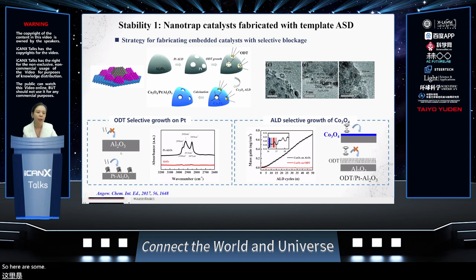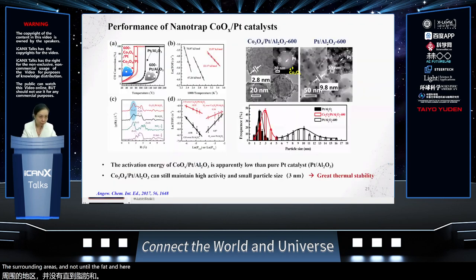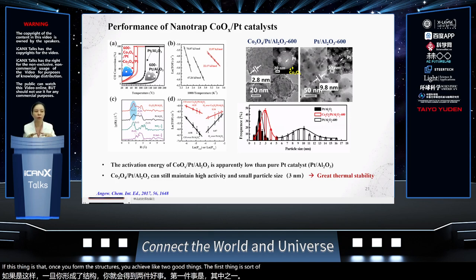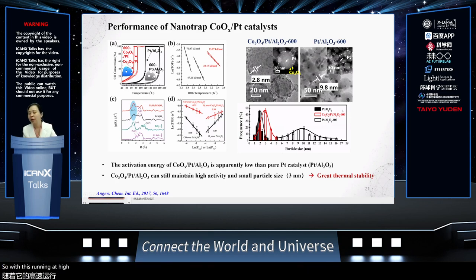Here are some proofs showing these two steps of selectivity. Basically, the passivation only happens on the metals, but not on the oxide. Later on, the ALD process only happens on the surrounding areas, but not on top. And here are the proofs. With this kind of structure, we are able to achieve this ball in the basket. The good thing is that once you form the structure, you achieve two good things. The first is that you anchor the structure, so when running at elevated temperatures, the particles are not significantly agglomerated. They almost keep the regular size as shown here.